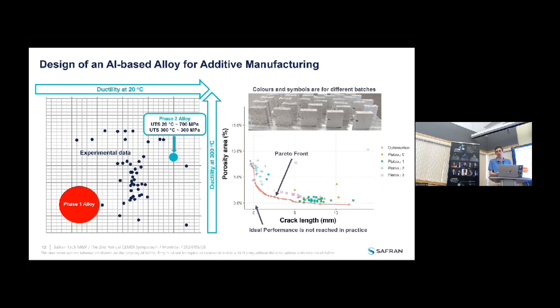Once this compositional optimization was done, we went on to do process optimization. So basically trying to customize the power of the laser, the speed of the laser, and the distance between the laser and the building plate. This is a result that we got. This is the porosity surface area that is measured when cutting the specimen in half. That gives you an idea of how porous the material is, how dense it is, represented as a function of the post-fabrication crack length when the stresses are relaxed. So the different colors there.